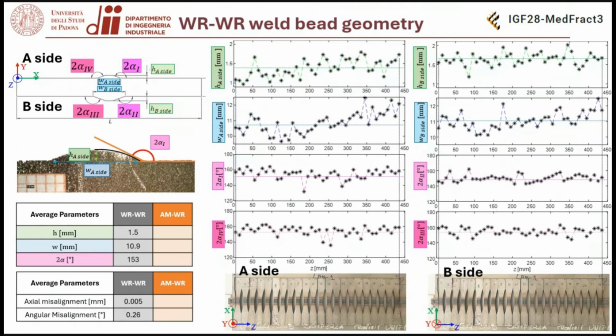We also carried out some tests with the strain gauge specimens in order to be sure that the bending induced by this misalignment was negligible, and it was. And also we verified that the loading ratio that we can measure with the strain gauges was the same that we assumed to apply, that was the theoretical one.